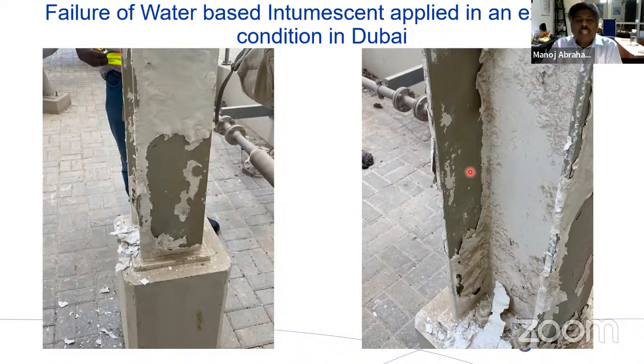So how do you define CX? If you take a piece of metal, carbon steel, and leave it outside, after 1 year, if you come and inspect, the loss of metal due to corrosion in one annum, in 365 days, if it is between 200 to 700 microns, 0.2 to 0.7 millimeters, then it is CX environment. If the corrosion loss of the metal in 1 year is between 80 to 200 microns, it is defined as C5 environment. If it is between 50 to 80 microns metal loss, it is C4 environment. This is how we define corrosion.